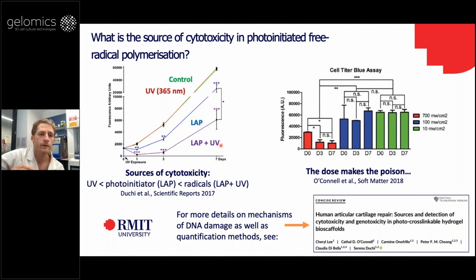In our case, we've done experiments studying what happens to our cells. We use mesenchymal stem cells, and look at what happens when we expose them to UV alone, to the photoinitiator alone, or to the photoinitiator plus the light. In this case, it's actually a 400 nanometer light, which is not technically UV, it's a bit on the cusp. Anyway, we found that by far the most toxic element was the free radicals produced when you have the combination of the photoinitiator and the light.